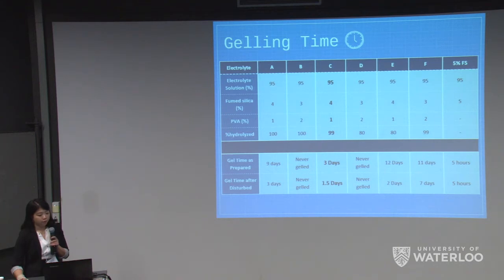And this depends on the solubility of the polymer, and the degree of hydrolysis is one of the factors that affects the solubility. Another factor taken into consideration when creating our gels was that, according to literature, a gel electrolyte cannot be obtained if more than 2% of the non-thixotropic additive, being PVA in our solution, or less than 3% fumed silica, the thixotropic additive, is used.